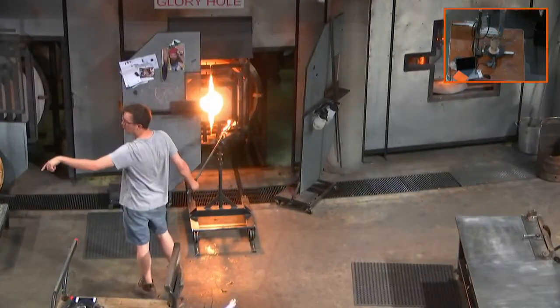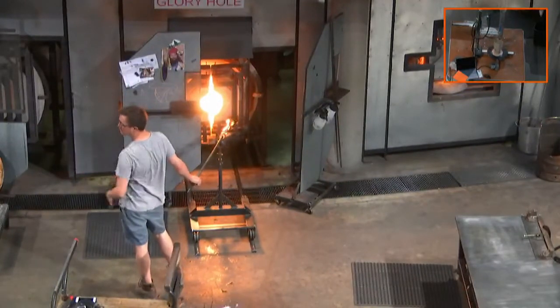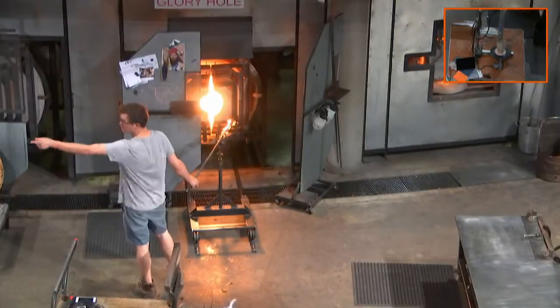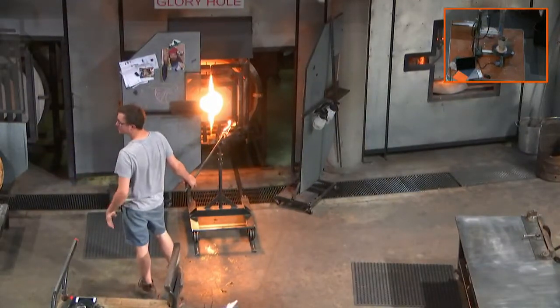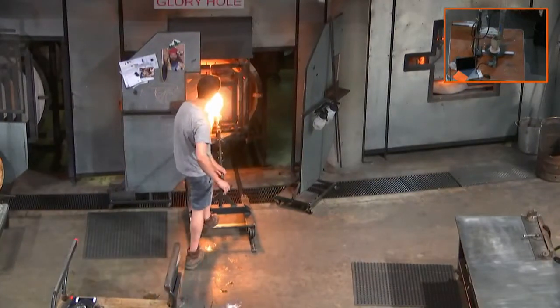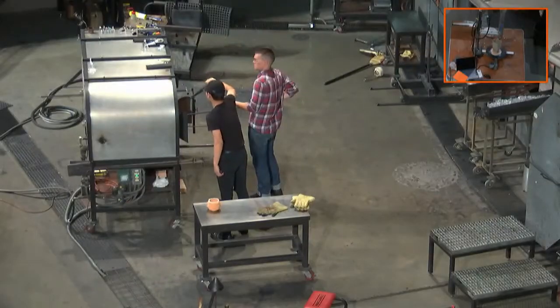What we're seeing is that when the ceramic is heated up, all that moisture is being sucked away, and the ceramic is shrinking over 15%. That's what's going on right here. That ceramic will constrict the glass, and that will cause it to break and crack.